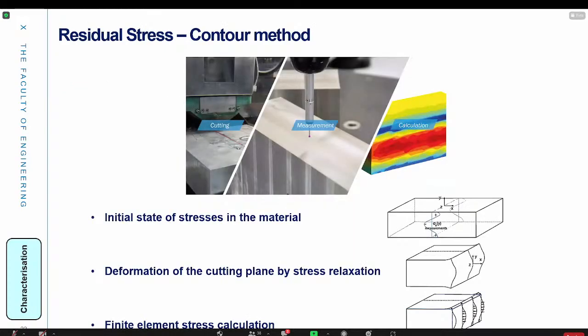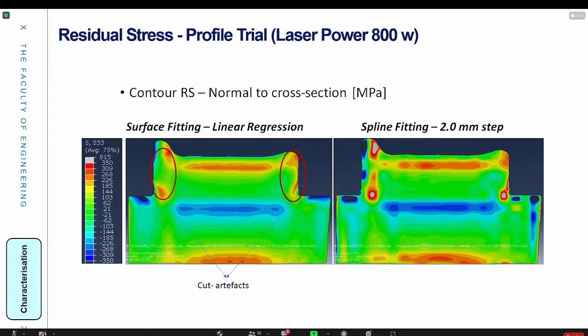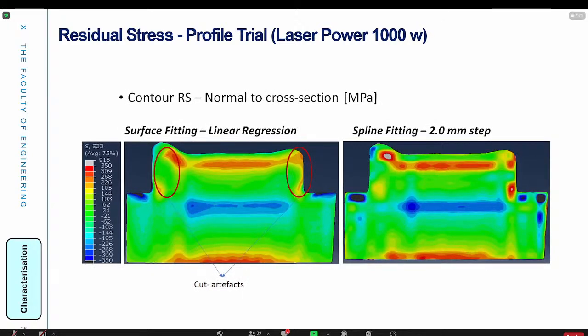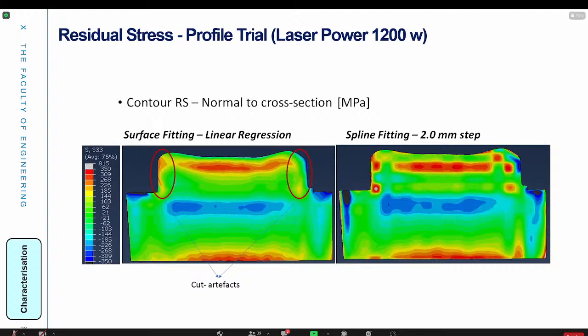The other thing we checked up to now is the residual stress, and we use the contour method system with the cutting, and then if we take the cut artifacts out, then we have a tensile. We find that we have a tensile residual stress, which is developed near the top part of the printed parts, and then we have a compressive residual stress developed around the interface. We checked that with different laser power, and we find the optimum of that.